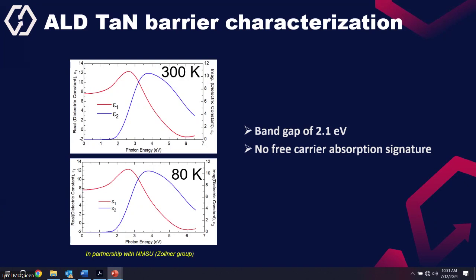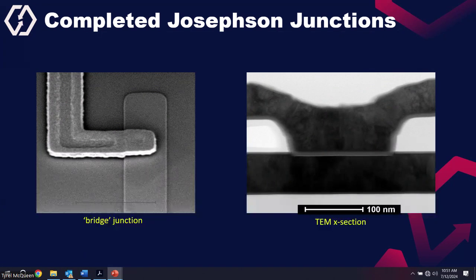So here we have established that we can use ALD tantalum nitride as a tunnel barrier. So then what's the next step? The next step is to do the top electrode patterning and deposition and etching. So this is how the final device looks like. The left-hand side shows the SEM image of the junction.